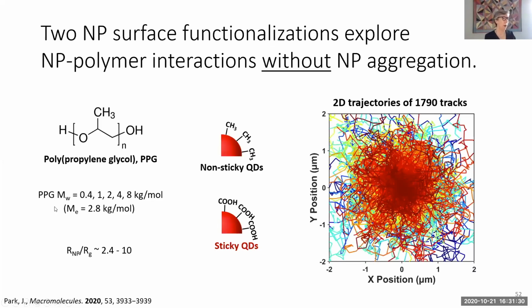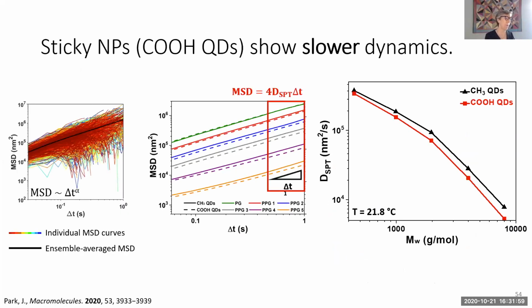And so here's our polymer. It's polypropylene glycol, nice low Tg material. And we looked at two particles, non-sticky, just with the methyl functionalization, and then sticky with the carboxylic acid groups. And this is just nearly 2,000 traces where we've started them all at 0, 0, and you can just see that it's nice and isotropic. And then you do a lot of analysis of those individual traces to back out the diffusion coefficients, right?